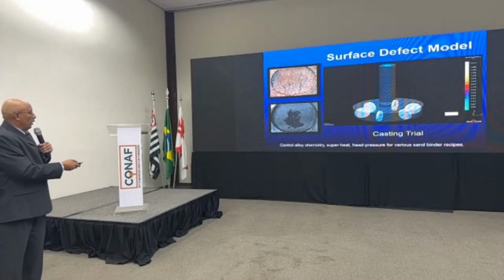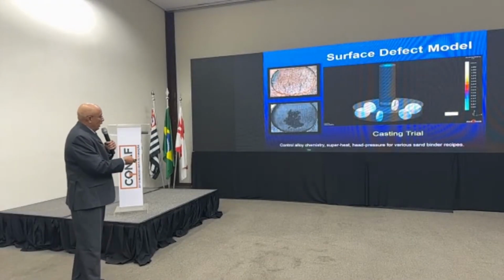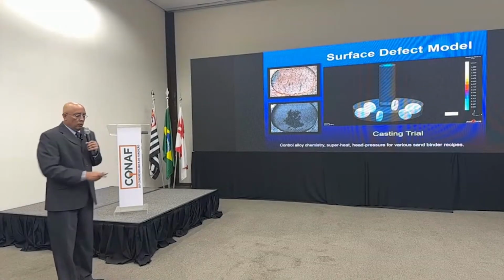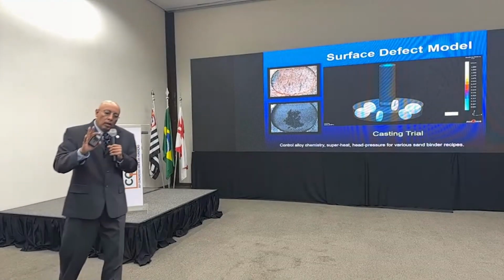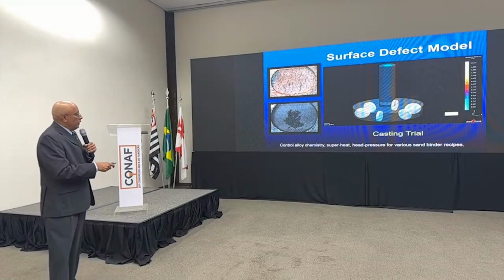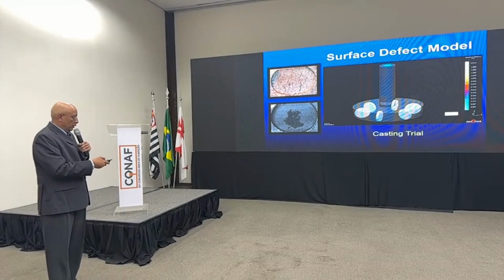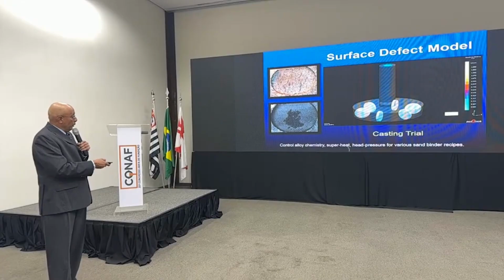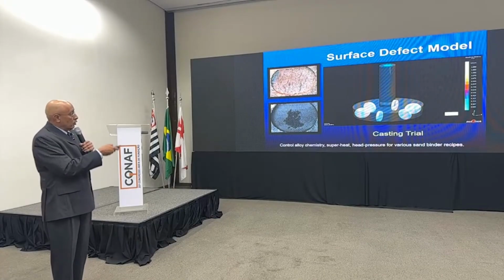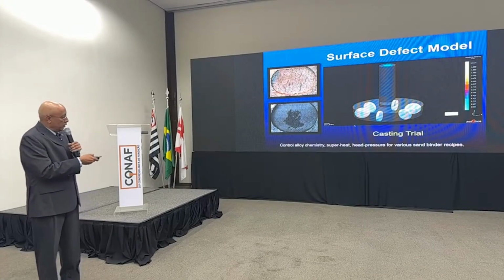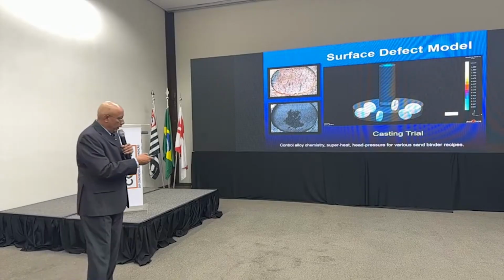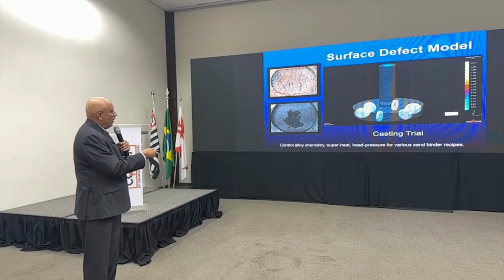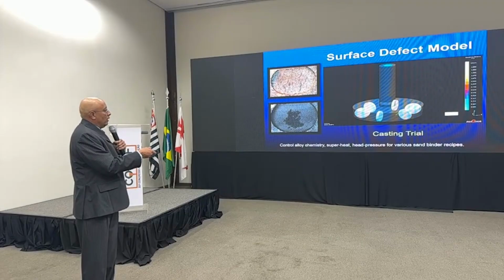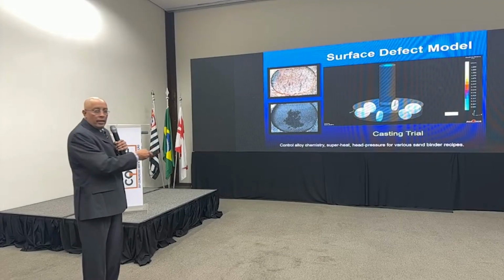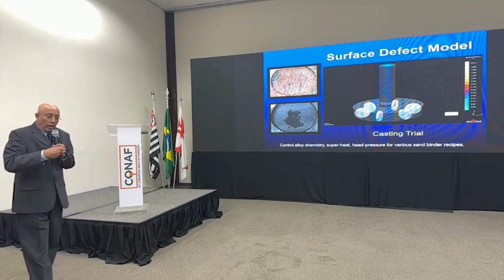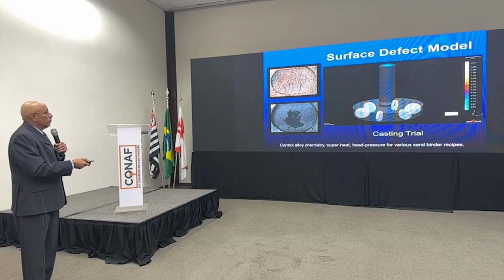Let me just back up here. So we are controlling the chemistry of the alloy. This trial is for a given alloy chemistry. And the superheat temperature, the temperature that we pour from, and the head pressure are controlled. We know what rho gh is for the various recipes that we can have: a silica sand, a ceramic sand, a blend, etc., a coated sand, and we study it in the same mold.